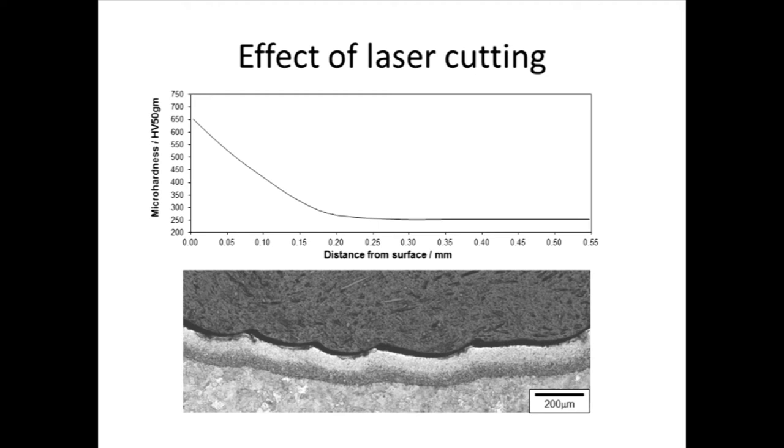Now, I said earlier on that we were expecting to be further processing the material by laser cutting, and so the effect of that on the material was also of interest. And when we looked at a laser cut edge of the material, we found that, as you might expect, there was a layer of martensite along the edge of the hole that was produced, and hardness rising to a very high level, which had some other practical concerns for us,